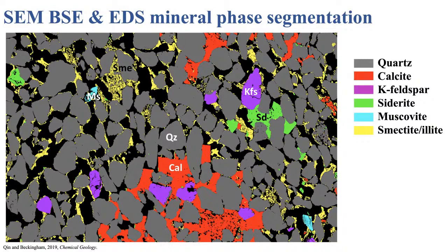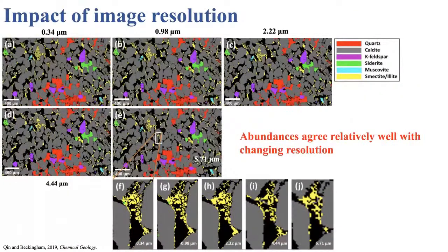Looking at mineral abundances, or the volume fractions that you get by just counting the pixels, we repeated this for 5 different resolutions from 0.3 microns to 5.7 microns, and then quantified the volume fractions and found really little variation among the different image resolutions. Now, if you zoom in here at the bottom, looking at some of the small scale features, though, and thinking about surface area and accessibility, we did see some variation in the accessibility of these different mineral phases.